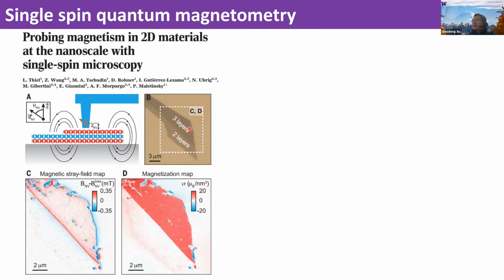already used this single spin quantum magnetometry to measure chromium triiodide. So in short, they have these trilayers, they have these bilayers, then they perform the spatial mappings. You can see that the sample is mostly homogeneous for the trilayer, right? You see magnetization, you see the stray field map, but the signal actually vanishes for the bilayer because, as I told you, bilayer doesn't have a net moment. They also observed these little tiny dots, which are defects, on the order of hundreds of nanometer scales. Another advantage of this magnetometry is that you can provide quantitative information on the magnetization in the systems. For example, for individual monolayers, the magnetization is on the order of 15, 16 μB. We cannot get this information from, for example, the magneto-optic Kerr effect. But single spin quantum magnetometry can give us these quantitative measurements.